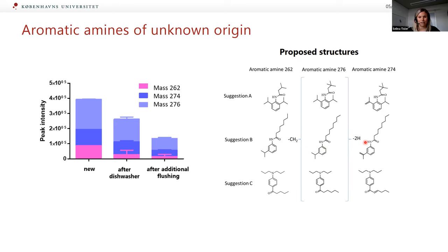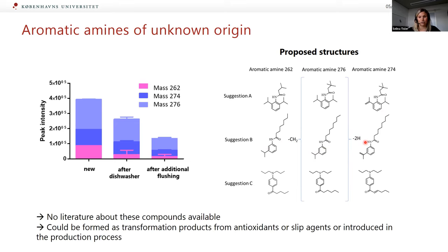And in general, the structures are fitting very well to these slip agents. So it could be that it's formed as a transformation product of the slip agents. But it also fits that they're antioxidants, with these groups here, which would be typical for antioxidants. So it could be they are formed during the use, but it could also be that these compounds are introduced during the production process.